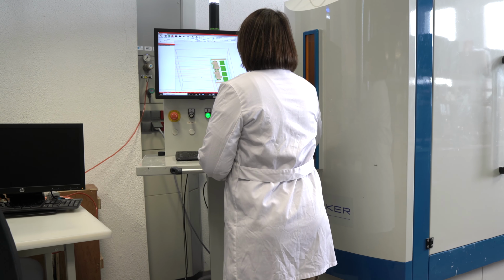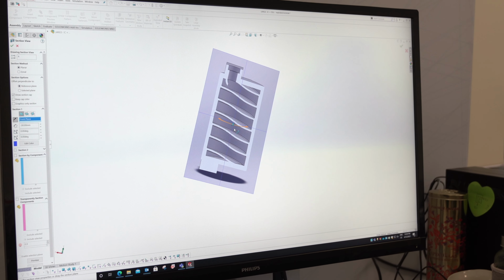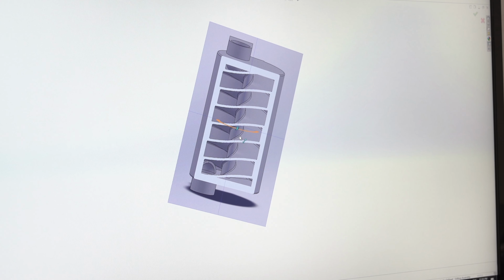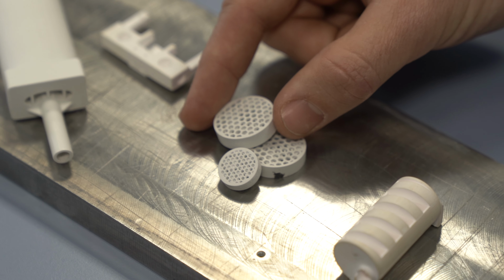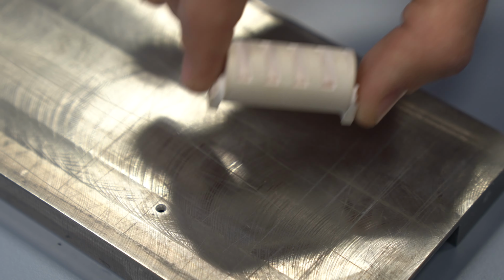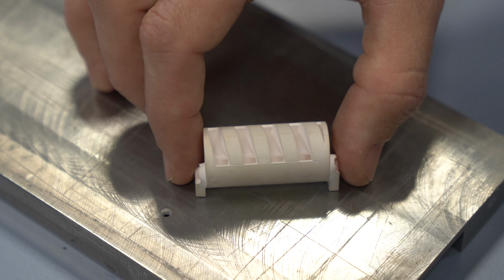The method allows the manufacturing of monolithic, complex geometries to improve the energy density, the performance, the thermal and fluidic management, or gas leakages by design. 3D printing of functional ceramics for energy applications reduces cost of implementation and the waste of raw materials compared to standard fabrication routes. The process allows making nearly free-shape solid oxide cells, widening the range of applications inaccessible up until now.